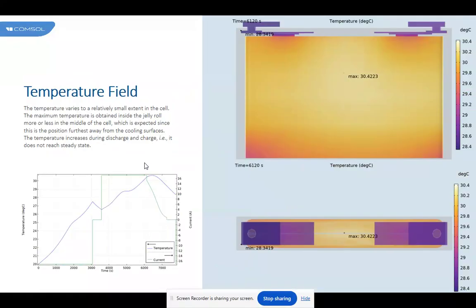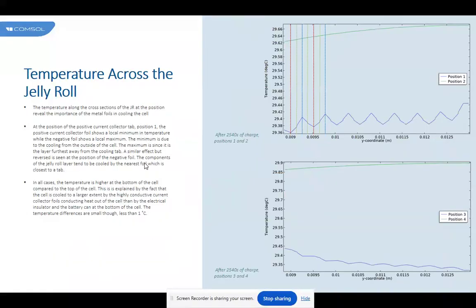Temperature field. The temperature varies to a relatively small extent in the cell. The maximum temperature is obtained inside the jelly roll, more or less in the middle of the cell, which is expected since this is the position furthest away from the cooling surfaces. The temperature increases during discharge and charge. i.e., it does not reach a steady state.